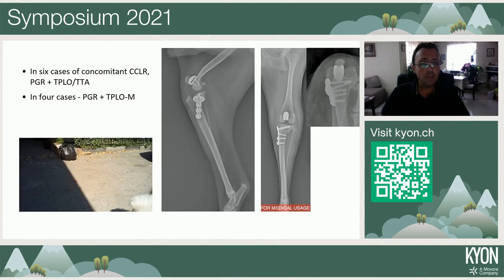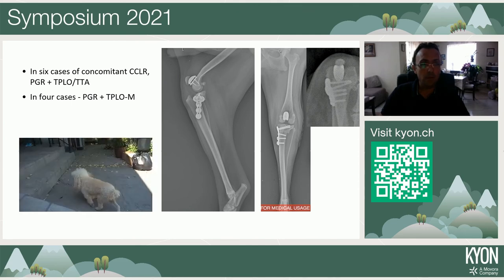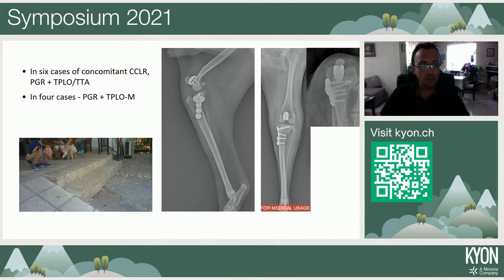Okay. In six of our cases, we had a combination of cranial cruciate ligament rupture together with a patellar groove replacement. In four of the cases, PGR was combined with TPLO, not surprisingly, because there are many cases of tibial torsion in these cases. So we used TPLO in order to compensate the tibial torsion. Here is one of the cases where we combined a PGR with TPLO.